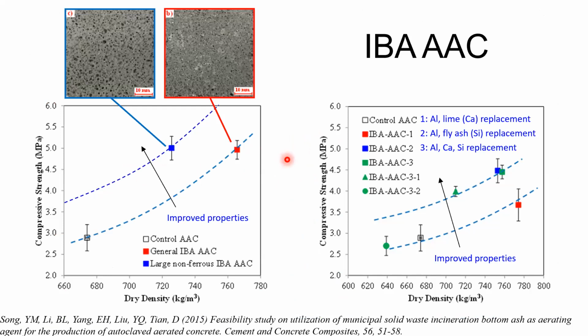In the lab, we tried to develop the resulting material compared with the control, reducing the density to about 700 kilogram per cubic meter. By using the large non-ferrous particles as the aerating agent, we are able to generate more gas and further reduce the density compared to without doing the size fraction sorting. Because of that, comparing these two lines, the strength versus density ratio is improved by using the non-ferrous IBA as the aerating agent.